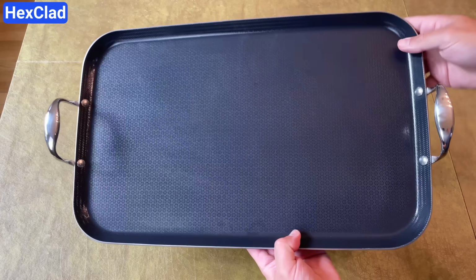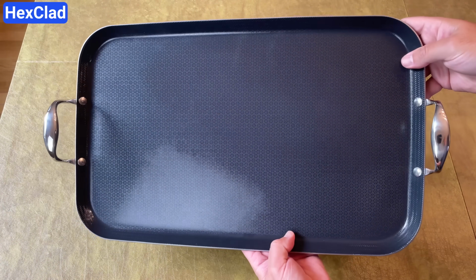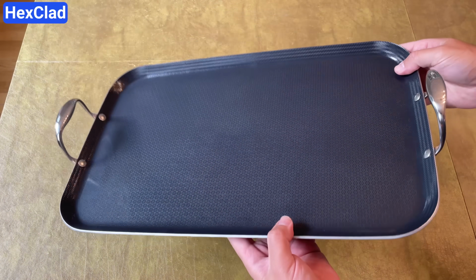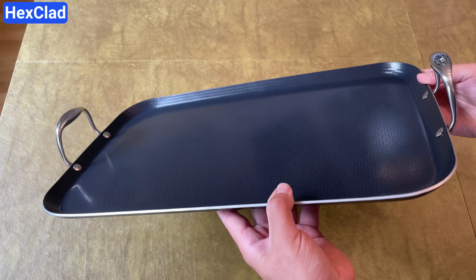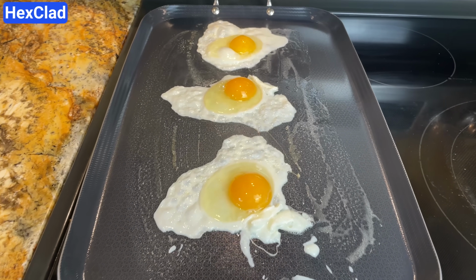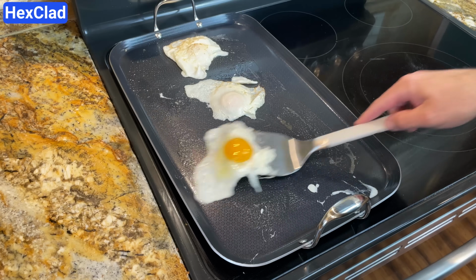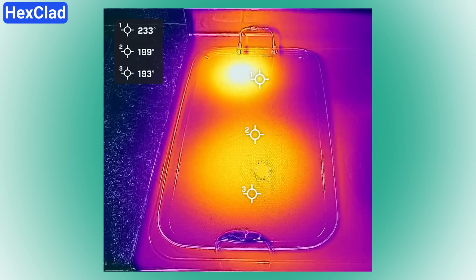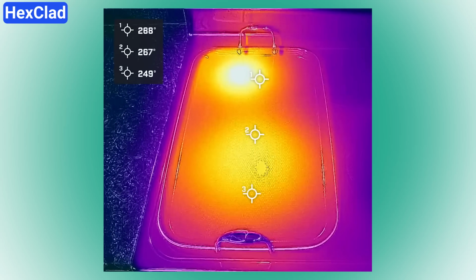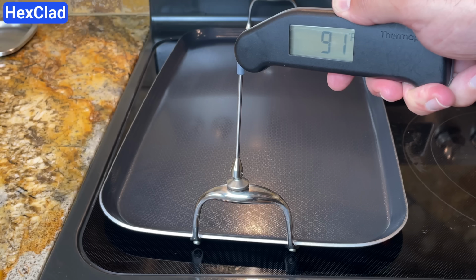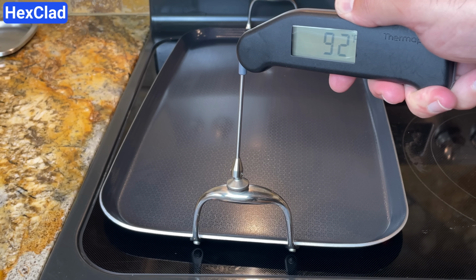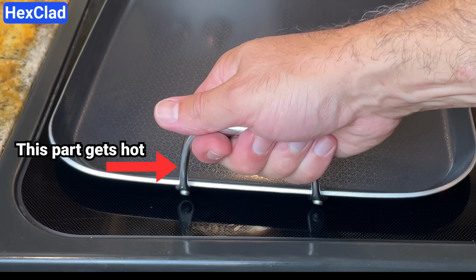And like all nonstick coatings, this ceramic layer will wear down over time, not just from scratches, but from heat and repeated use. That said, while the coating lasts, the performance is excellent. Eggs slid right off and cleanup was easy. It also heated more evenly than the other griddles, with the smallest temperature difference between the hottest and coldest spots. I like the vertical handles too. The tops stay cool, although the stems closer to the pan do get hot.